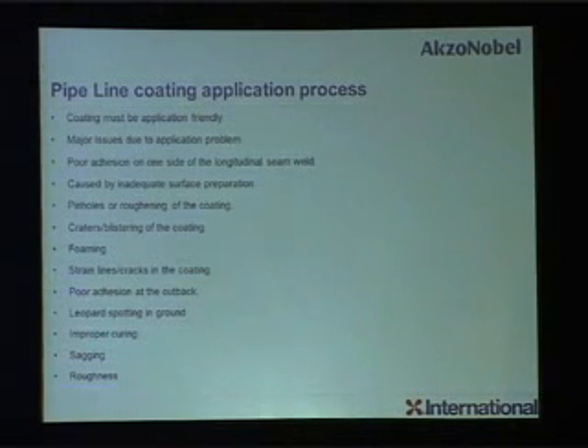If you are not able to give a small amount of allowance to the sites, they are not able to go for scale up. Like, in the lab I can do 3:1, but in the field, in production, whether exactly 3:1 is possible, or we have to give plus minus 5%, something like that. So what I'm trying to tell is the coating must be application friendly. We need to understand how much application deviation should be possible at line, and we should take care of that. Major issues due to application problems, we must understand and must emphasize during the PQT or during the discussion between the coating applicator and coating manufacturer.